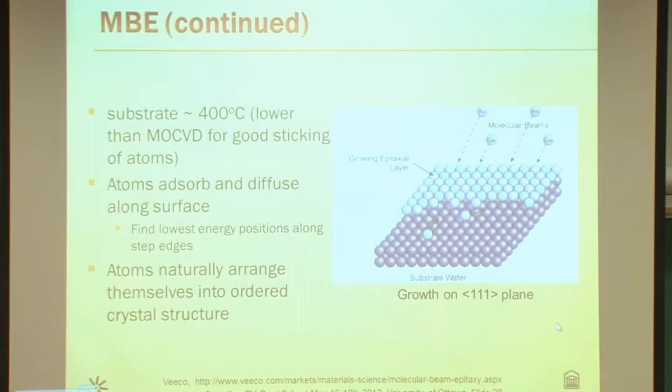The substrate's held at about 400 degrees C. That's lower than MOCVD, as we'll see. It's a good temperature for atoms, when they hit the surface, to stick to it. Atoms can move along the step a little bit to find a nice step edge to position themselves. And then as those atoms move around, they naturally arrange themselves in the ordered crystal structure of the underlying substrate.